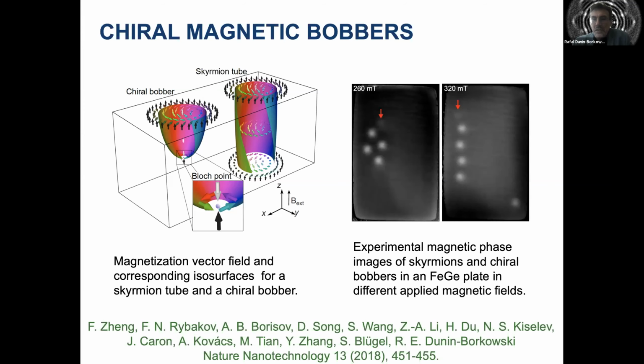These were predicted and then imaged using off-axis holography. On the right are phase images recorded in the electron microscope, and the red arrows point to chiral bobbers, which have the same size as magnetic skyrmions, but have weaker contrast, but they've never been imaged in 3 dimensions.